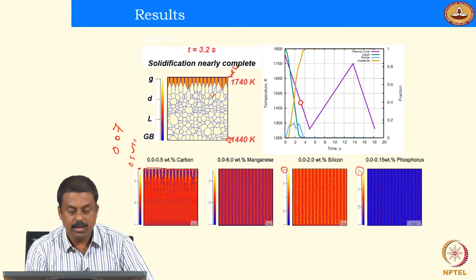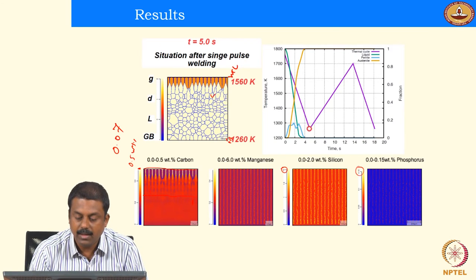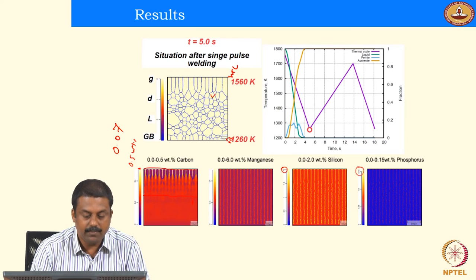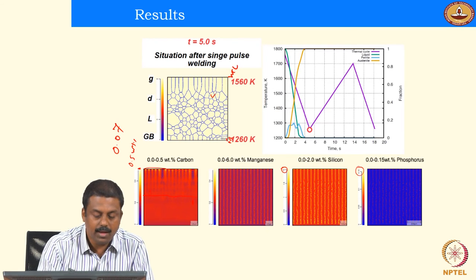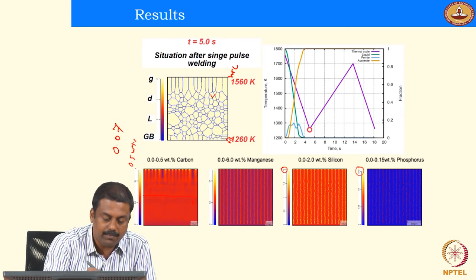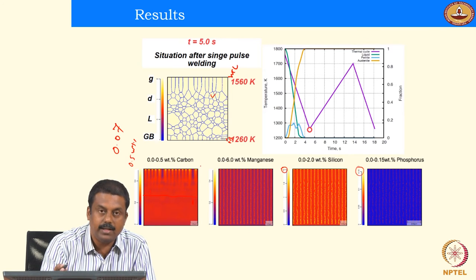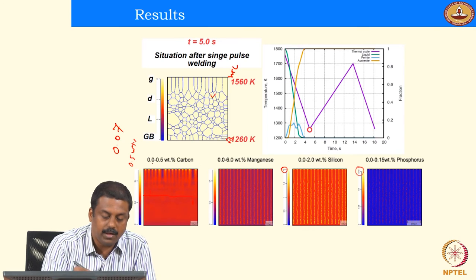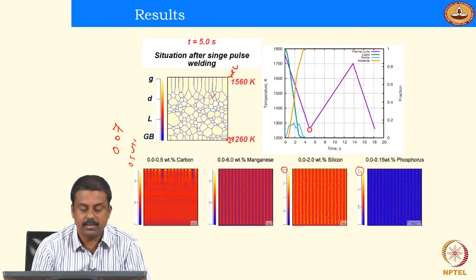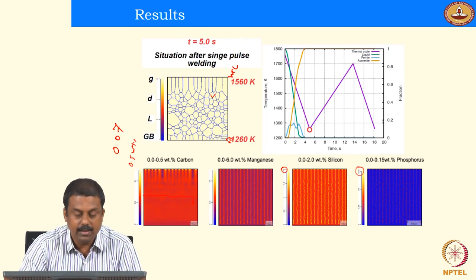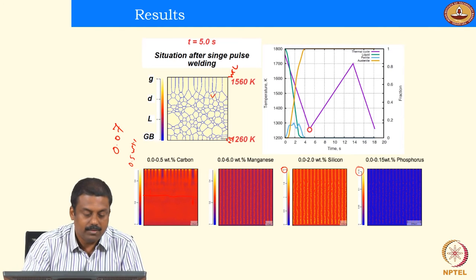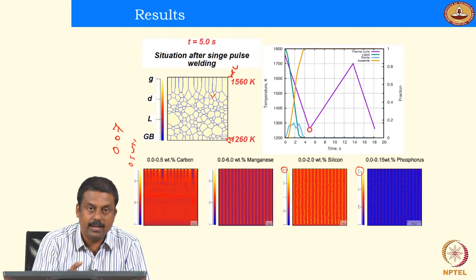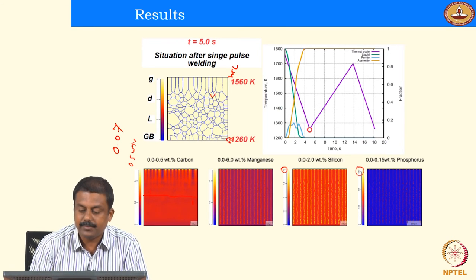Okay, and subsequently if you cool down, at this point solidification is completed, and you see a significant amount of segregation, that's the weld center line segregation we always study, right? So the weld center line is now enriched in carbon. Carbon concentration is as high as 0.5, even if you begin with much less. So this is the region where we expect an interface failure to happen at the weld center line.